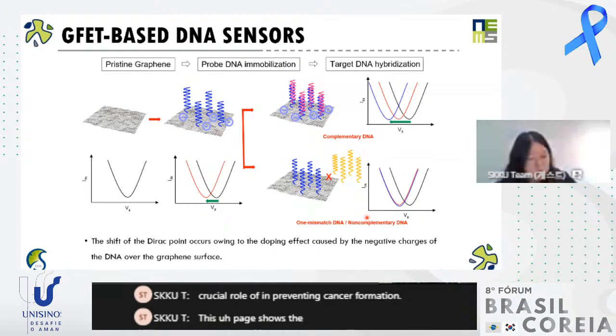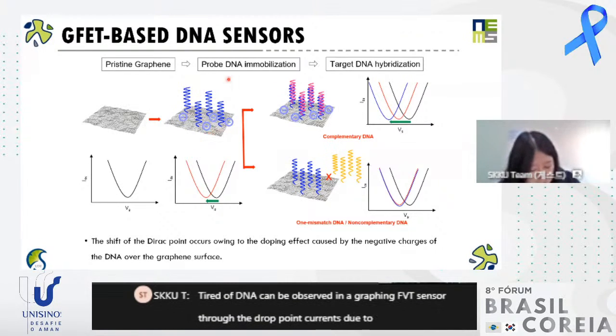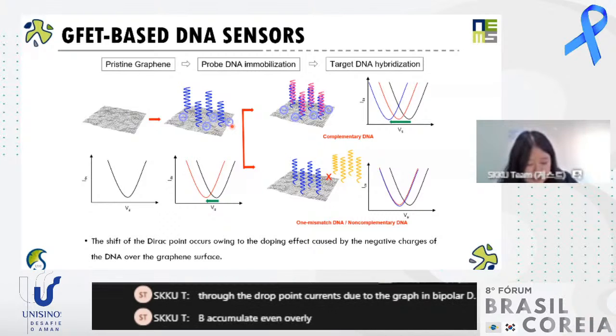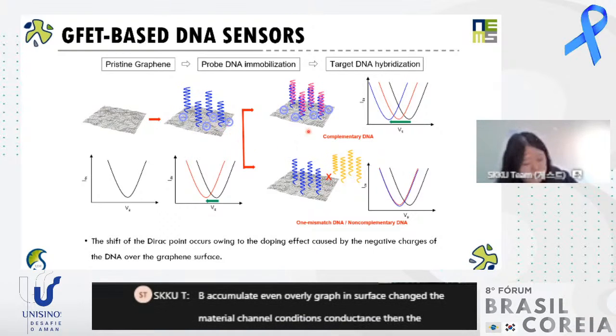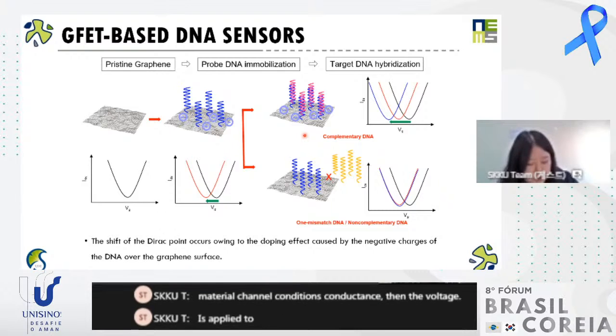This page shows the mechanism to detect DNA using a graphene FET-based sensor. The negative electrical charge of DNA can be observed in a graphene FET sensor through the Dirac point, due to graphene's bipolarity. The ions accumulated over the graphene surface change the channel conductance. Then voltage is applied to the gate terminal, and the negative DNA charges increase the ion concentration over the graphene, changing its channel conductance.